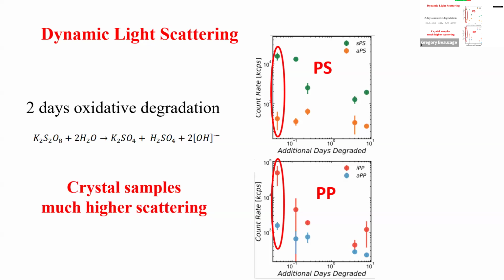So what we do is we take our sample, in this case polypropylene, and we put it in a flask. Polypropylene doesn't degrade, so we use potassium persulfate to speed up the degradation process. You put the polypropylene film in there, potassium persulfate breaks bonds in the amorphous phase, and then you watch. Then we remove the film and do light scattering. Light scattering tells you if you have objects that are big. If there are lots of big objects, you get lots of scattering. If you have no objects in solution, you get no scattering. That's the way you want to think about it.